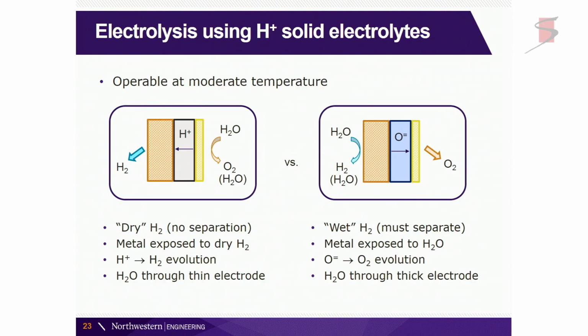And there are issues also, let me describe this point. If you're bringing steam through this thin electrode, we don't run into mass diffusion limitations in the way that there are mass diffusion limitations here. So that ties into the fact that we don't want to have a lot of steam here, but we have to have a lot of steam because the steam has got to diffuse through this rather thick layer, which is maybe a few millimeters in thickness, whereas here the steam is only going through something like 20 microns. So we have to have a high concentration so that we don't have a mass diffusion loss, yet we have nickel that we're going to oxidize, and that becomes a problem. Now, the hydrogen evolution happens here, and those overpotentials are typically quite small, so you don't drive bubble formation and therefore delamination, whereas in the case of oxygen evolution, overpotentials tend to be high and become enough to create bubbles and cracks, and that becomes a problem for this system.